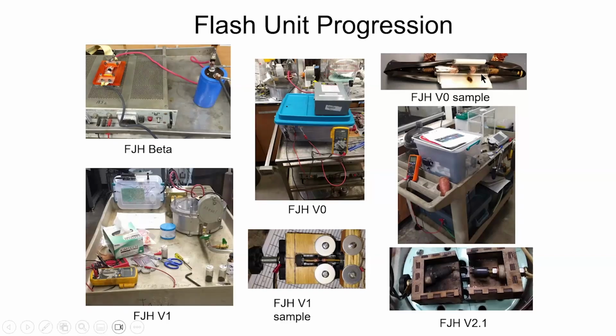He then took a quartz tube, he put the sample in there, put these wads of copper wool, and then he just took brass screws and stuck them in the ends as the electrodes. You see the brass screws? And then how are you going to keep this pushed down? So he just put electrical tape around it. Just kind of push it in there. He would see that when he would flash it, the electrical tape would get too hot and just melt away. So he just put some paper in between the electrical tape and that, just to keep it a little bit off of that.